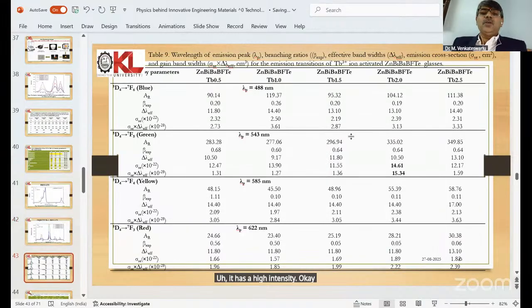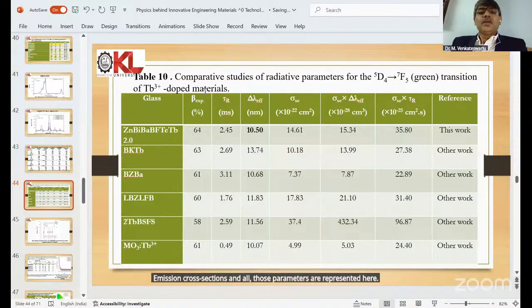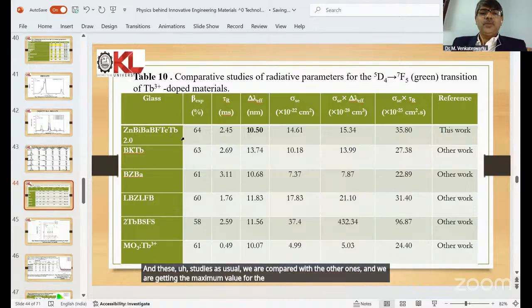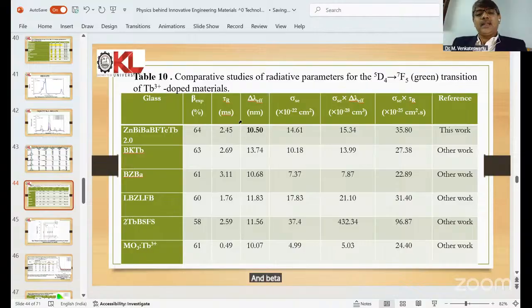Using those emission spectra, we have calculated the transition probability, branching ratios, emission cross sections, and so on. Those parameters are represented here. As usual, these studies are compared with other works, and we are getting the maximum value for the 2.0 sample, with beta experimental of 64 and sigma SE of 14.61, and it is compared with the literature survey.